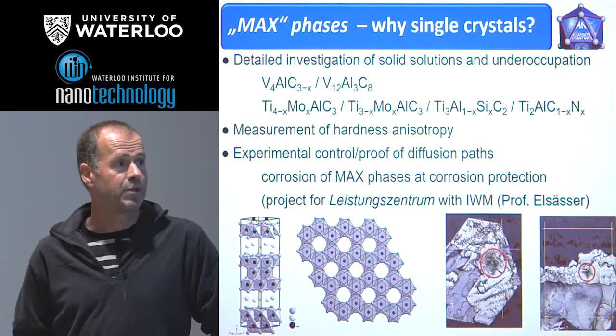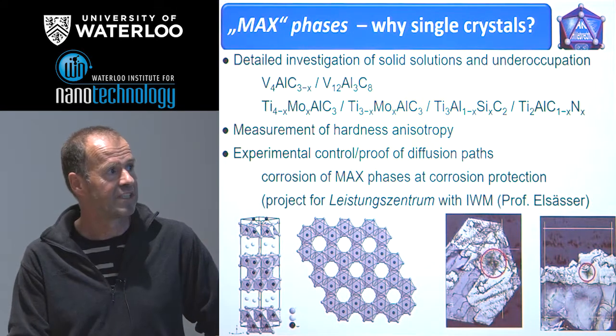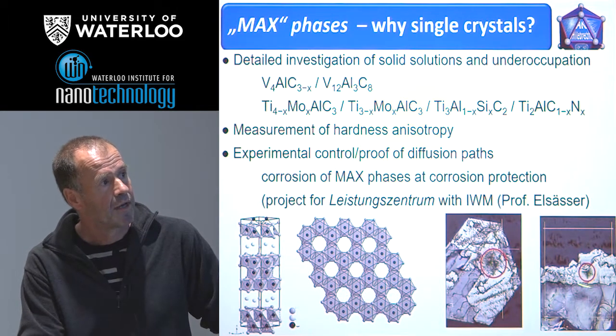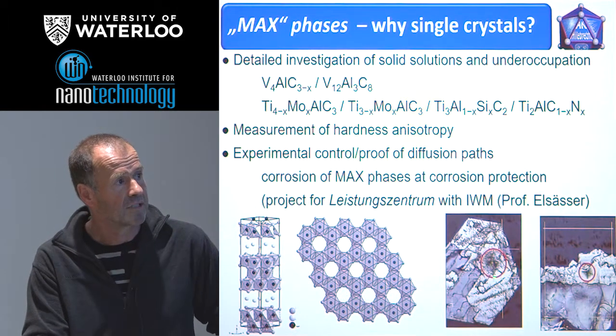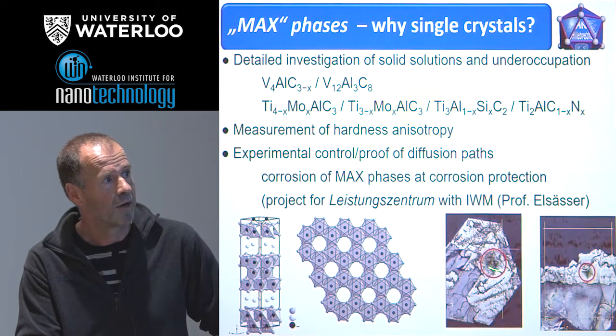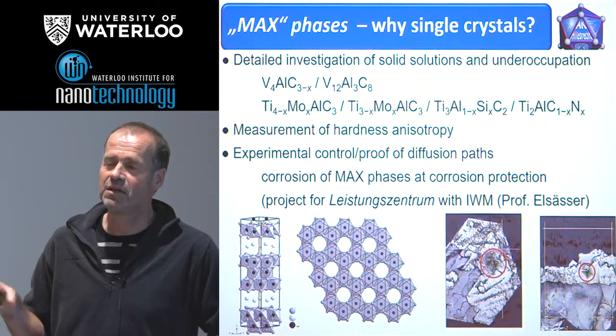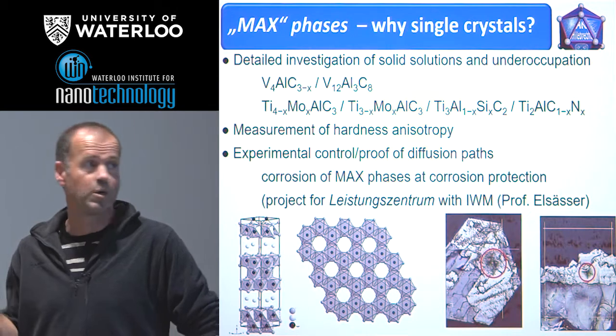So that's possible, and we could show for the first example, to be true the second example, that the hardness of the crystals is strongly anisotropic, about a factor of 2, similar to the values which were calculated.